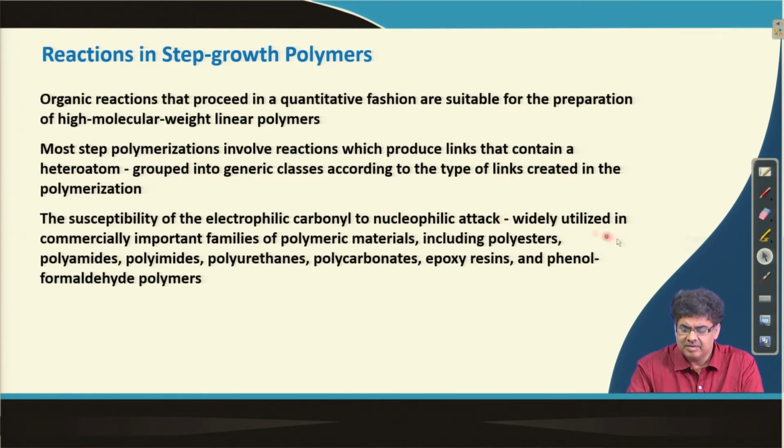There are many step polymers which have the carbonyl group. Now, because of the delta positive charge on carbon, the carbonyl group is prone to nucleophilic attack, which is very useful for synthesizing commercially important families of polymer materials like polyesters, polyamides, polyimides, polyurethanes, polycarbonates and so on.